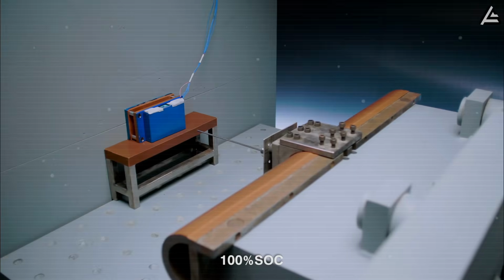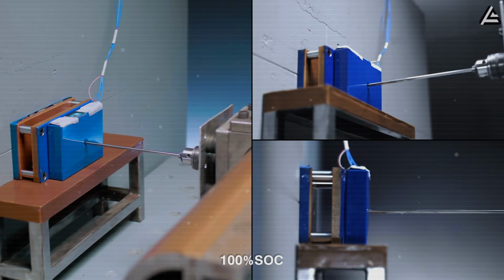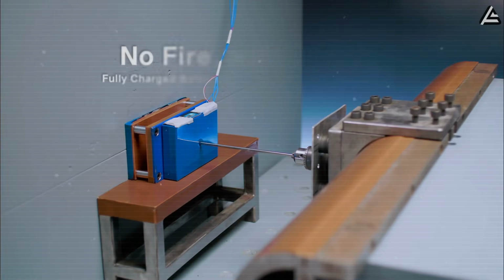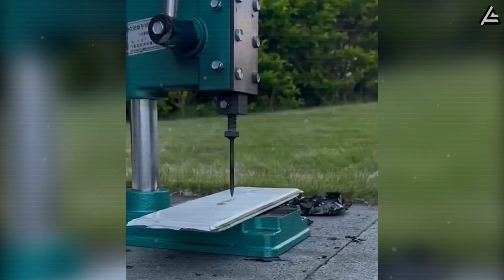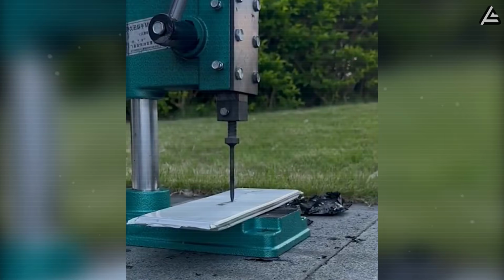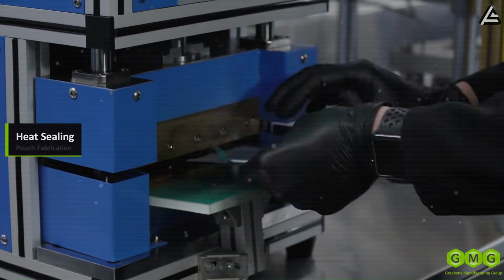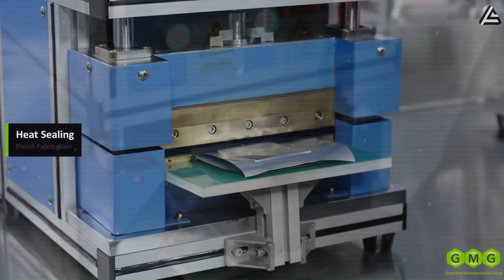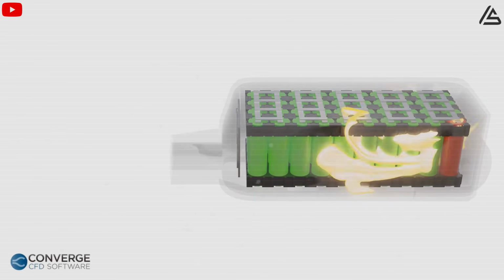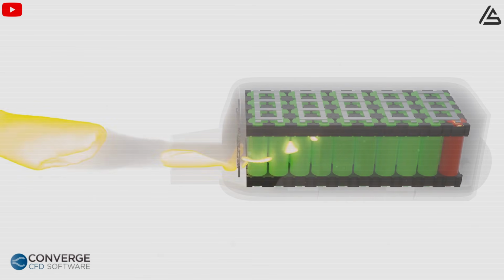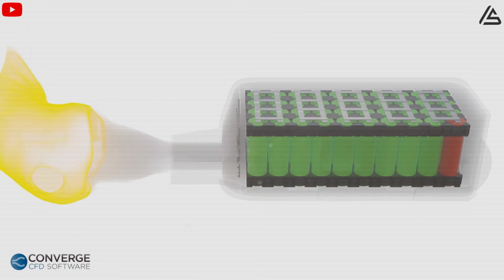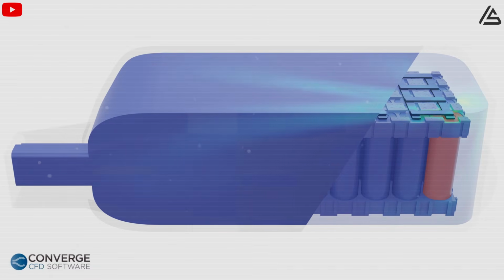When deliberately punctured with a steel nail, cell temperature rose by just 8 degrees Celsius before stabilizing, compared to 200 to 250 degrees Celsius spikes in standard lithium-ion under identical conditions. The numbers are just as striking in overcharge testing. When driven to 200% of rated capacity, lithium-ion packs typically vent gas within 90 seconds. Aluminum-ion cells, by contrast, show no combustion, no outgassing, and maintain normal voltage behavior.